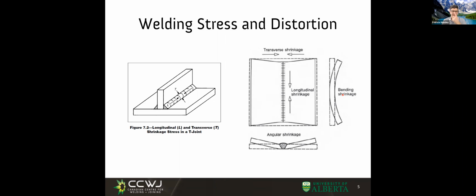Way back in the 90s, when I was still doing my PhD, one of my lab mates was doing additive manufacturing of Inconel using electron beam welding. Incredibly pioneering work. And they were using no preheat, and the residual stresses as they were building a wall layer after layer were so big that this banana you see here, it looked pretty much like this. I couldn't believe how distorted things were.